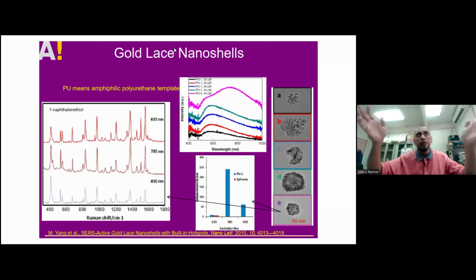It maybe depends on the molecular structure of the surfactant, whether it's a long chain or short chain surfactant, or whether it's an anionic surfactant or a cationic surfactant, because you have different types, right? You have anionic surfactants, you have cationic surfactants, and some of these work on different principles. So you have to be sure which type of surfactant you use. But the function of surfactant is basically to disperse the nanoparticles so that they remain as a colloidal suspension.